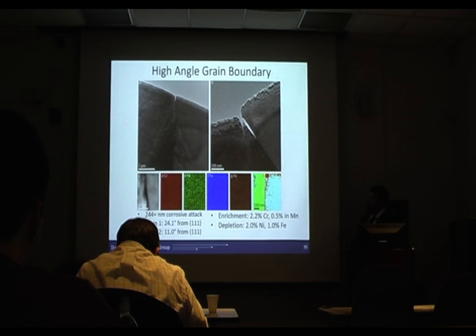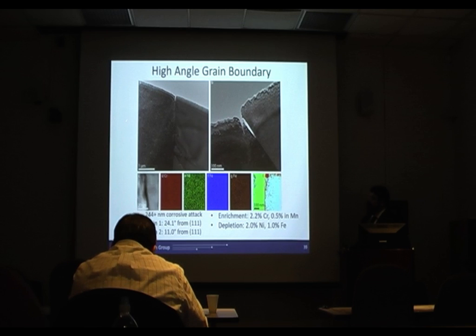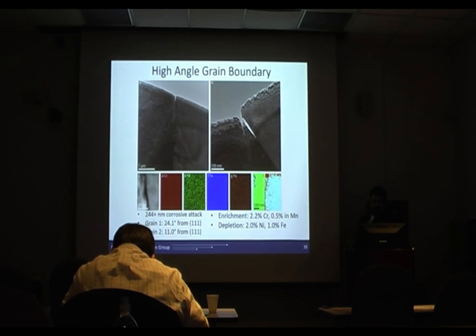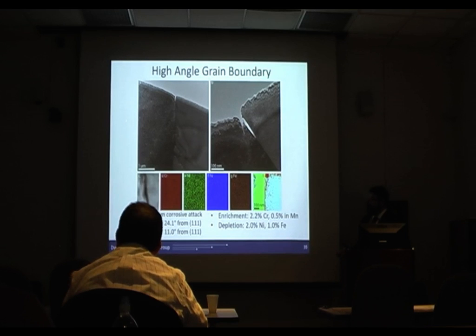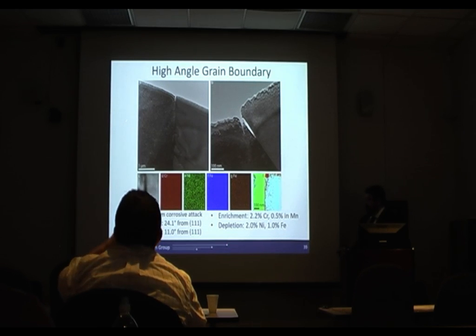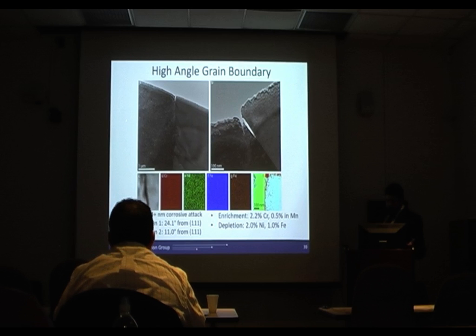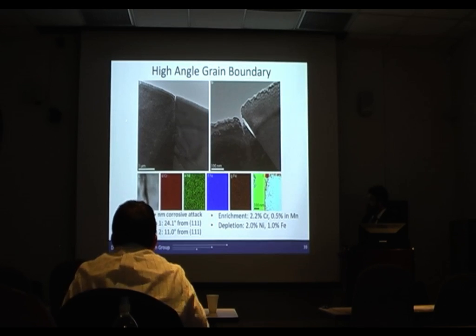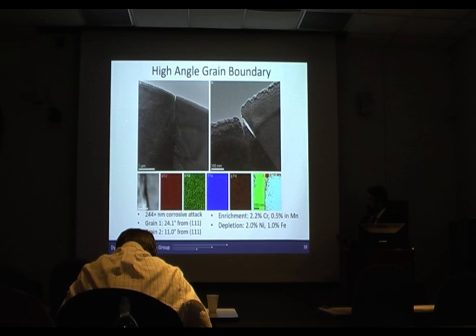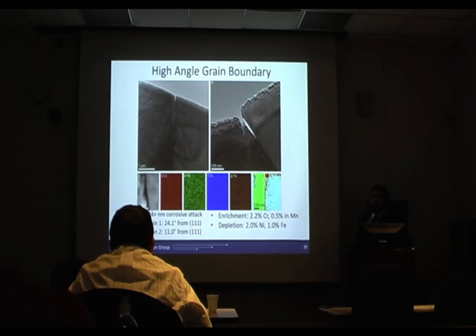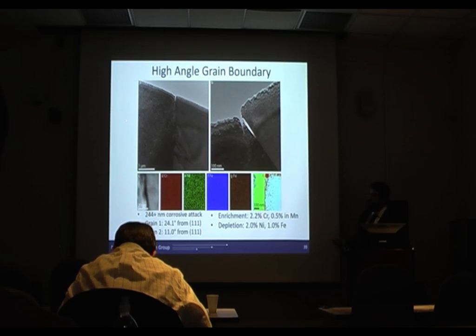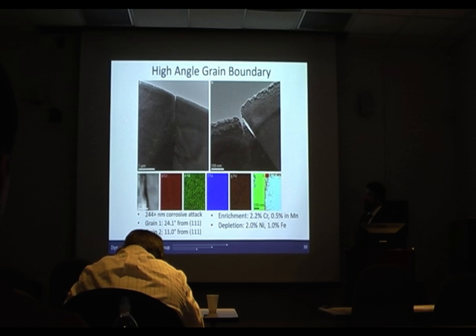And what we found was we actually accidentally milled away our platinum coat at the top, but we still saw over 240 nanometers of corrosive attack, and neither grain is terribly close to a 111 crystal plane, being at least 11 degrees away. The enrichment of chromium is about 2% and about 0.5% in manganese, and then we depleted about 2% in nickel and 1% in iron at the grain boundary. It's a little bit hard to see in these maps, especially on the projector, but those numbers were generated by integrating a large area across the grain boundaries.